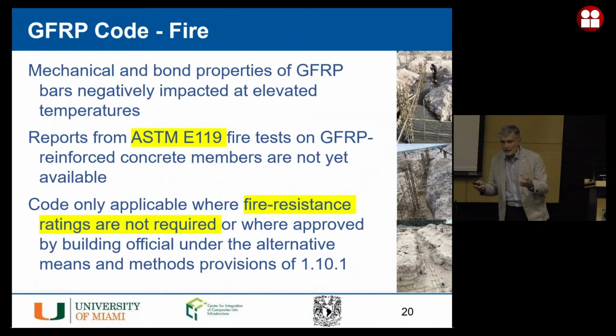Actually, again, another challenge. Let me explain this, and then again, with your faculty, you can work it out. If I reach a temperature, let's say, of around 400 C, steel loses its modulus of elasticity, right? So now all of a sudden at 400 C, if this truss is a reinforced concrete truss, this truss will be on my head, right? Not because I destroy the steel, but because I lose the modulus of elasticity. In the case of an FRP, if I get to 400 C, what happens? Well, the resin will dissolve. That vinyl ester will disappear, not even burn, disappear. But the fibers will stay. So if you have the FRP anchored, then fire is not an issue. Just the opposite. You can reach probably 1,000 C before you see the failure of the structure.